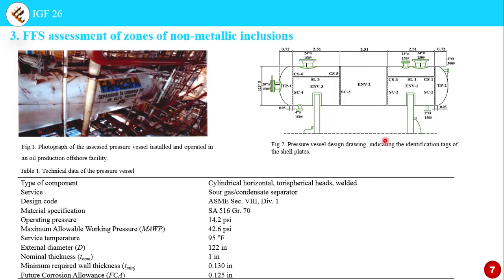This slide shows the photograph of assessed pressure vessels, along with pressure vessel designs indicating the identification tag. And we found the non-metallic inclusion zones in the heads and the cylindrical section of these pressure vessels. Here in this area, and this area, and this area, we found the non-metallic inclusion zones.